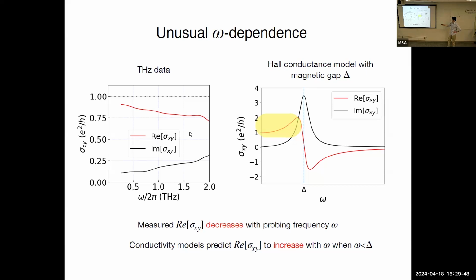So we see this frequency dependence, which is decreasing with frequency, as you can see here. And it was a little puzzling because in most known theoretical models for this Hall conductance, we expected to see sigma xy increase with frequency first and then decrease, which is quite the opposite in this case. So we started questioning.